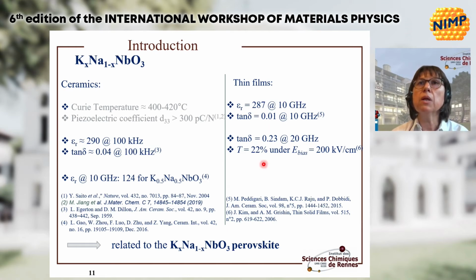Concerning the possibility to tune the frequency of a device, for instance, the tunability T has been reported to be about 22% under 200 kilovolt per centimeter as E bias. The tangent delta is typically 0.23 in this application at 20 gigahertz. So all these data are related to the KNN perovskite.